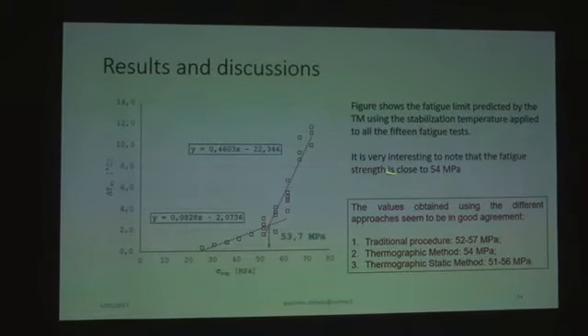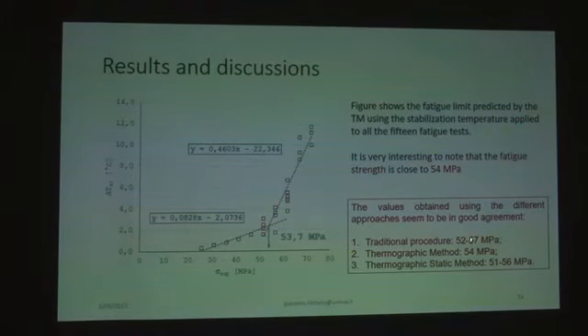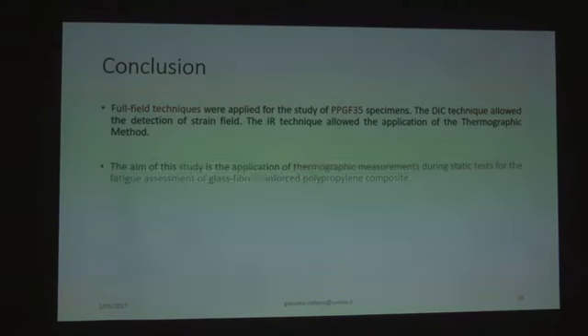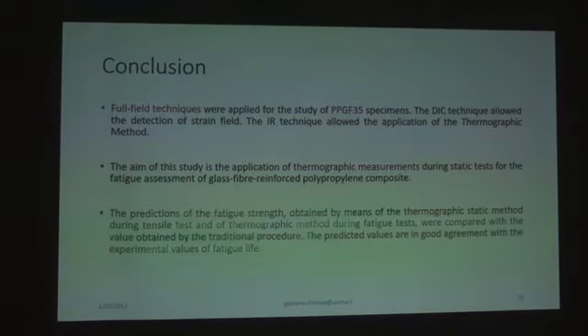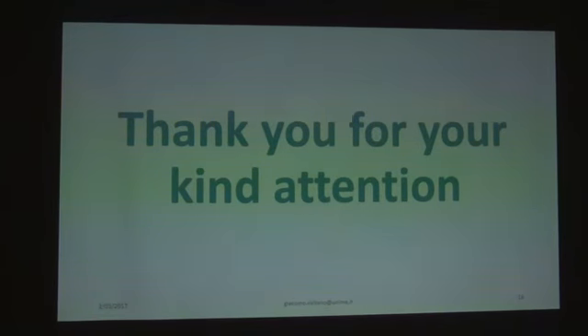In summary, we can see that with the traditional approach, we have this value of fatigue limit. For the classical thermographic method during fatigue test, we have this value, and after, with the new thermographic static method, you can see this value. In conclusion, we use a full field technique for the strain field, and a full field technique for the temperature of the specimen, and we can see that there is a good agreement with the experimental value, with the classic thermographic method, with the new approach we propose, and with the classical method to have the fatigue limit. Thank you for your kind attention.